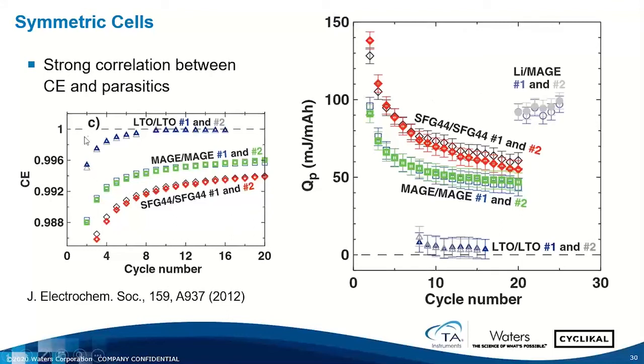We also back up most of these experiments with our high precision electrochemistry measurements. And you can see these are correlated very well with the thermal results. So the titanate, almost perfect Coulombic efficiency, resulting in almost complete absence of thermal parasitics.